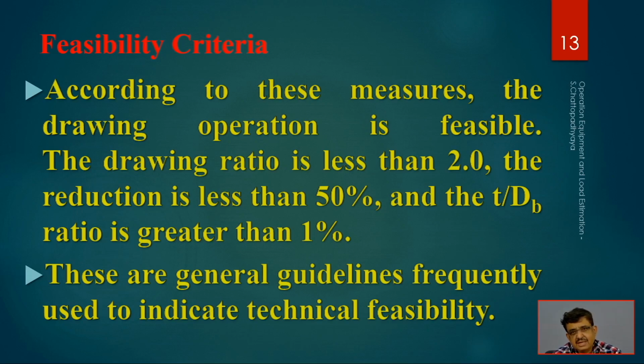So it is feasible. The drawing ratio is less than 2, and the percentage reduction is less than 50%, and the T by DB ratio is greater than 1%, because the thickness is not so thin that it is less than 1% of the initial blank diameter. So in both cases it satisfies the condition, so the drawing is feasible. These are the first two criteria that have to be tested for drawability. These are general guidelines frequently used to indicate technical feasibility. We have to see whether we are able to do the process as per the standards, guidelines and manuals. These two ratios give only a very preliminary, blunt assessment of the feasibility of the process.